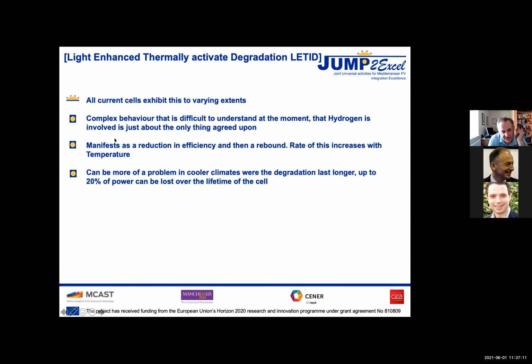What happens is even more strange: we get a reduction in efficiency from exposure to light. The rate of reduction depends on temperature, hence the thermally activated, light-induced degradation. And then it rebounds afterwards. So you end up with a cell which is as efficient after it's gone through this process.